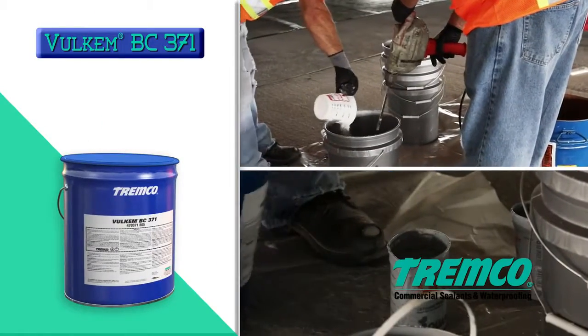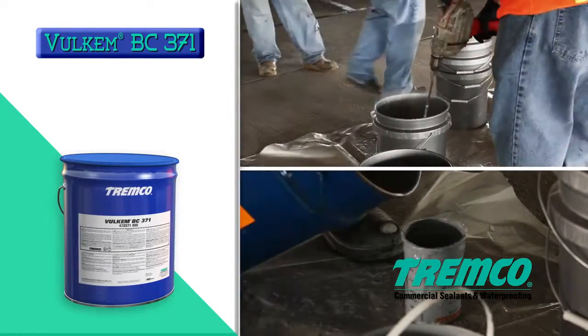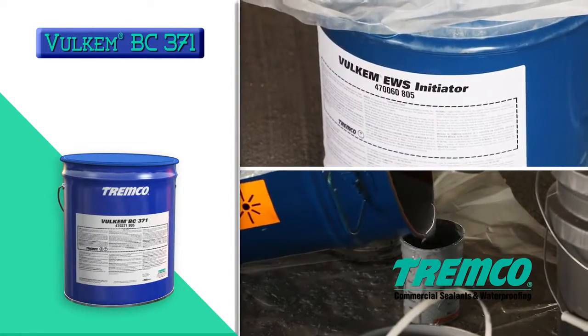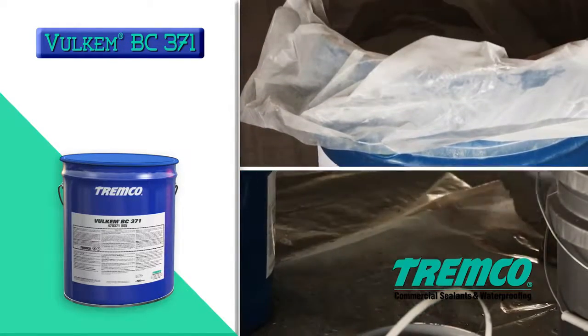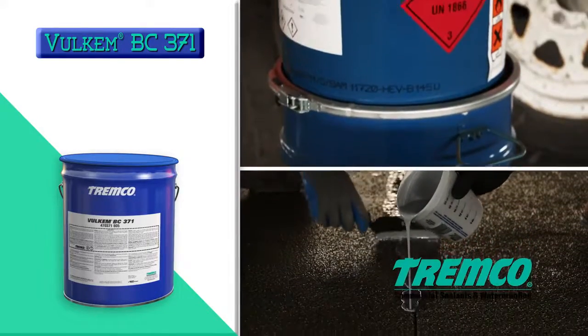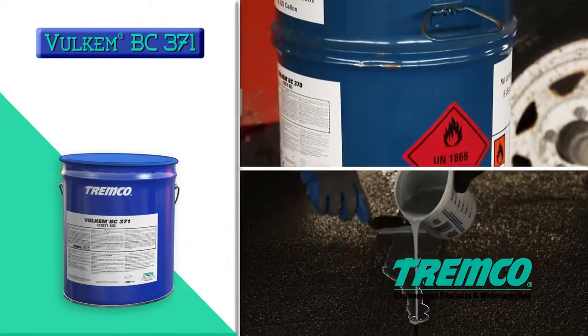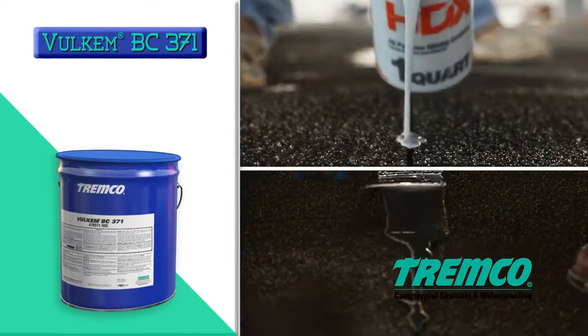For moving joints, mix Vulkem BC371 for 2 to 3 minutes prior to the addition of Vulkem EWS Initiator. Ensure Vulkem BC371 is thoroughly mixed together with the Vulkem EWS Initiator. The amount of Vulkem EWS Initiator is dependent on the ambient temperature. Please refer to Table 3 of the application instructions for addition amounts.